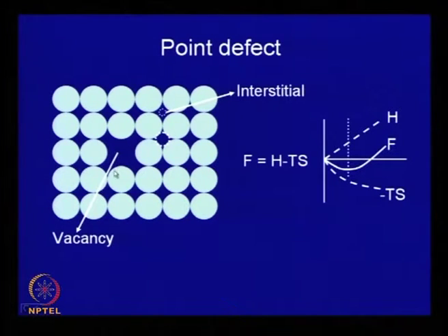So, basically, the vacancies can be arranged at random, and this causes a disorder in the structure. You increase more vacancy, you increase the disorder. Therefore, the entropy of the system increases. And if you want to create a vacancy, you have to give some energy, and if you want to create more vacancy, you have to spend more energy. So, H is moving like this, and the entropy increases with the disorder, but the overall effect here is minus TS. So, this is negative, this decreases like this.